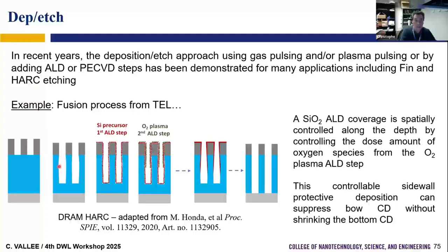So what you can do is that during the process, you can add some ALD step, and depending on the ALD step and the control of the ALD, you can deposit only on the top. And so you can deposit where you are losing some materials to try to redefine the profile and then to propagate a very good profile for the etching.